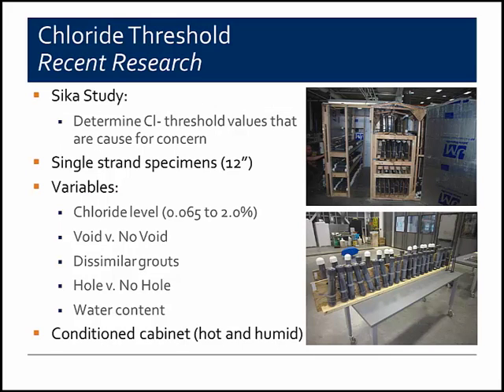And so, to supplement all of this available information, Sika has instituted a research program. And the goal of the program was to determine the chloride threshold values that are cause for concern for corrosion. The program consists of single strand specimens, a 12-inch long piece that is dropped into a plastic tube and grouted. And the variables were the chloride content of the grout, whether or not there was a void in the sample. They modeled repair conditions where you have a high chloride grout on the bottom and a no chloride grout on top. In some samples, holes were drilled into the side of the plastic tube to increase oxygen availability, and then the water content of the grout was also varied. And all of these samples were stored within a conditioned cabinet that was generally kept hot and humid.